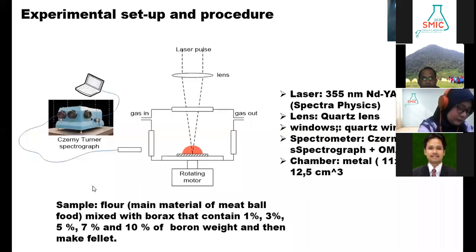The sample used in this experiment is not really the meatball sample ready for consume, but we use the main material of meatball food, its flour, mixed with borax that contain 1%, 3%, 5%, 7%, and 10% of boron weight, and then make pellet. We don't use the meatball food ready for consume because it is still wet and difficult to attach to the sample holder.